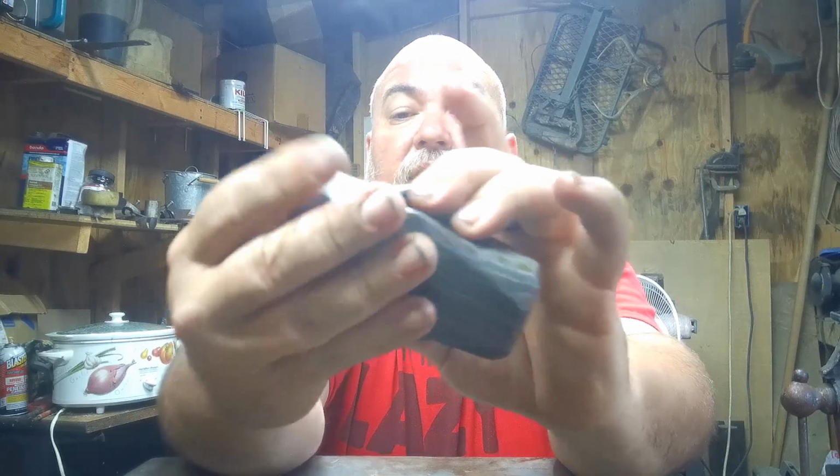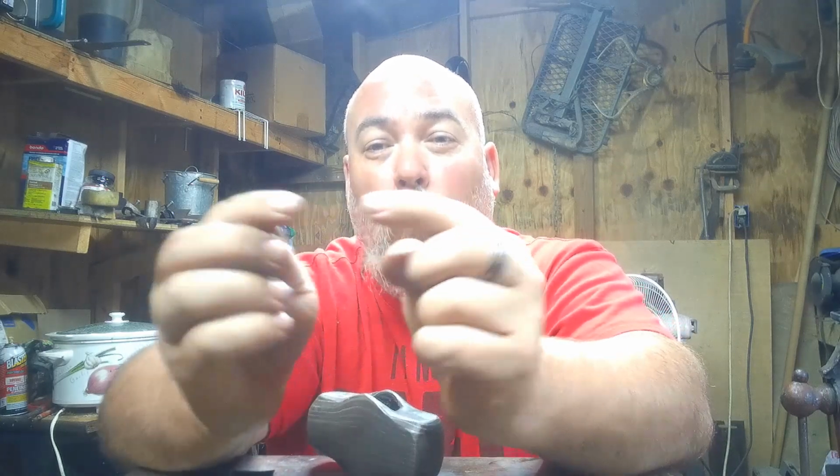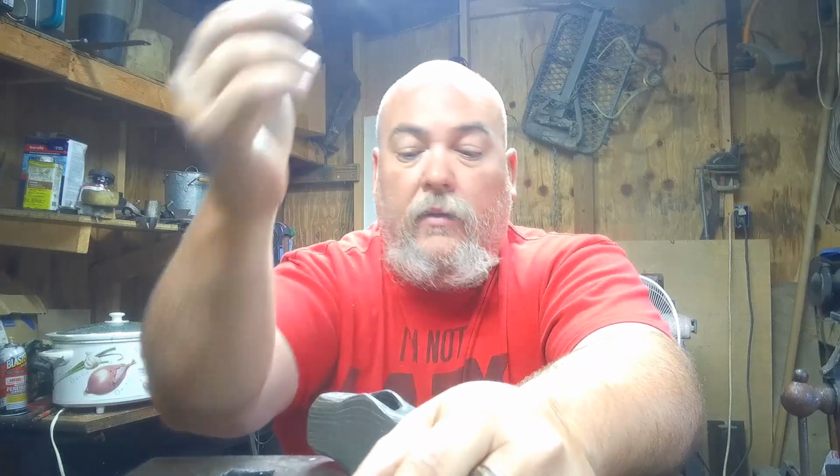I think what that came from is when I was stacking everything, I had it somewhat level or the same distance or thickness, but not perfectly. So I think when I welded them, some of the edges rolled, cold shut, and didn't weld, which would have been done away with had I done brand new stock.